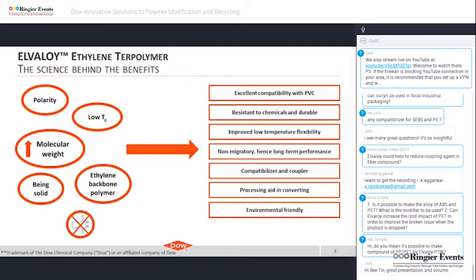hence it improves low temperature flexibility of PVC. PVC has a molecular weight of between 50,000 to 150,000 and Elvaloy has a molecular weight of between 250,000 to 400,000. Hence, Elvaloy polymer gives higher tensile strength and higher tear resistance to the vinyl compound when it is used as a modifier to PVC. Unlike liquid plasticizer, Elvaloy will not migrate to the surface of PVC due to its high molecular weight. Hence, it prevents brittle failure and improves long-term performance of flexible PVC sheet, component or parts.